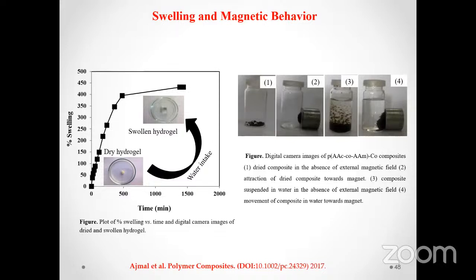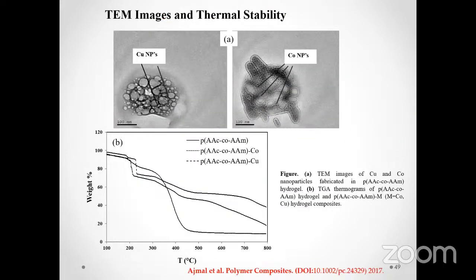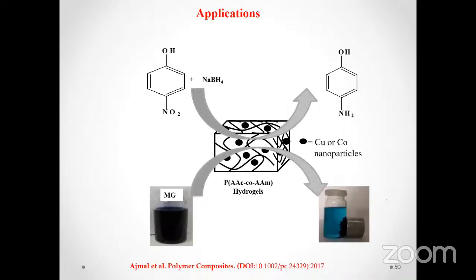even in these bulk hydrogel systems, no matter whether those composites are present in dried form or suspended in a reaction medium. Here are the TEM images, and cobalt nanoparticles can be seen very easily, that very fine, spherical cobalt nanoparticles of around 10 nanometers were prepared. In this system, thermal stability was again observed about 200 degrees centigrade. So this system can also be used at industrial scale. This was used as an adsorbent as well as a catalyst for the reaction medium.